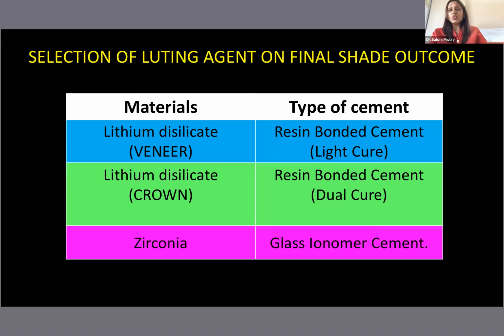Now, mind you, when you're using dual cure, nowadays we have amine-free dual cure resin cements also available, because dual cure resin cements have amine in them. And those amines, which are photoinitiators of dual cure resin cements with benzoyl peroxides, over time cause discoloration. So that's why it is judicious, particularly in the anterior aesthetic zone, to select the amine-free resin luting agent, particularly when you have a translucent ceramic which you're using in the anterior aesthetic zone.